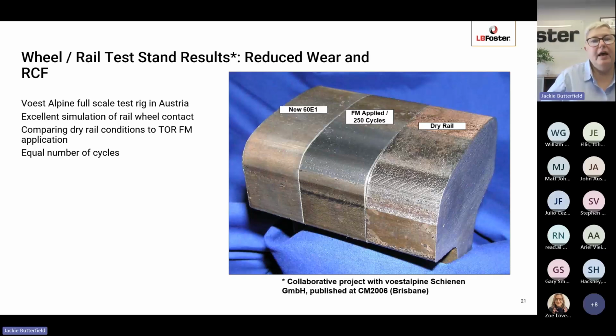And you can see that the rail is pristine. There's no damage at all to it. And then on the right, you have a dry rail that's gone through the same amount of cycles as the FM applied rail. And you can see very clearly that you have rolling contact fatigue cracks forming on the gauge corner, and you also have wear. So you can see the difference in profile between the top of rail applied rail and also the dry rail.